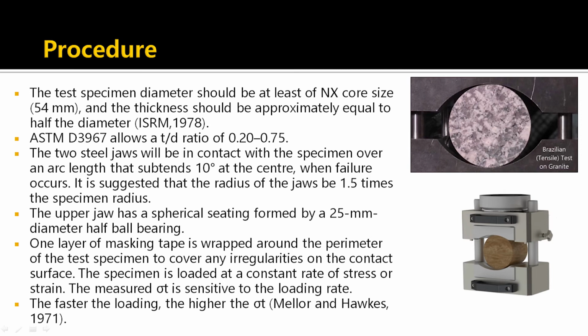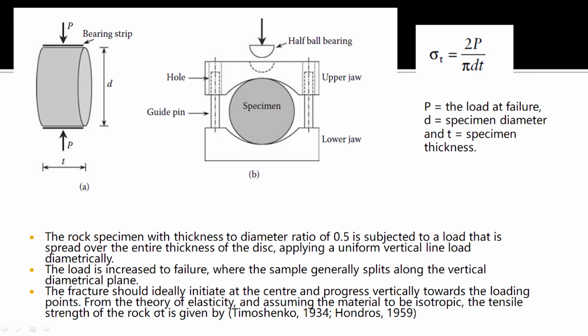Another thing that is crucial here is the rate of loading. If you have a higher, swifter rate of loading, the load taken by the sample would be higher as against a slower loading rate. Here in this image you can see the specimen, the cage, both upper jaw and the lower jaw. So you have a half ball bearing on the upper end on which the load is applied, right? And the load at which the failure takes place gives the tensile strength, or sigma T, which is equal to 2P by pi D T. Here P is the load at failure, D is the diameter of the sample, T is the thickness of the disc.